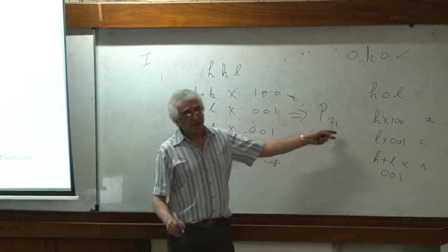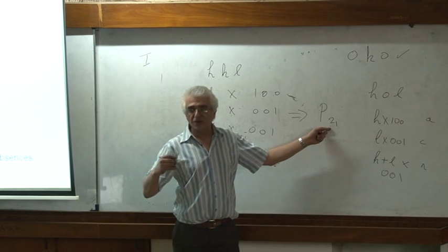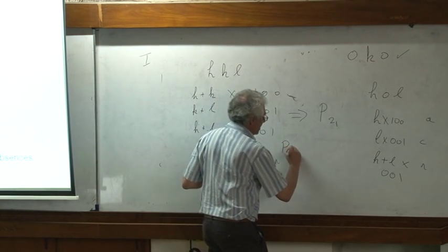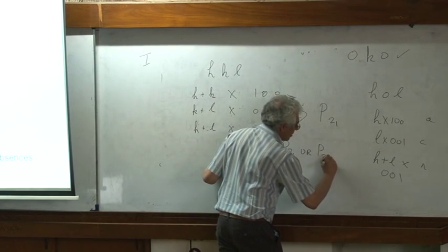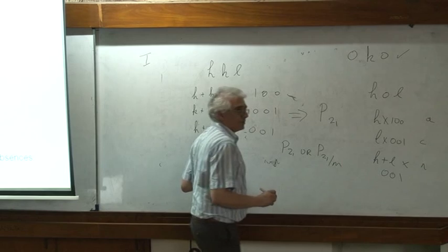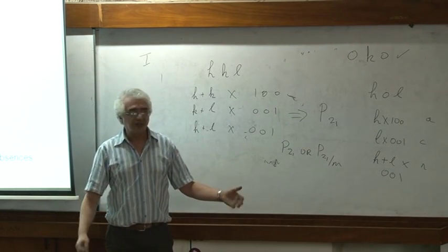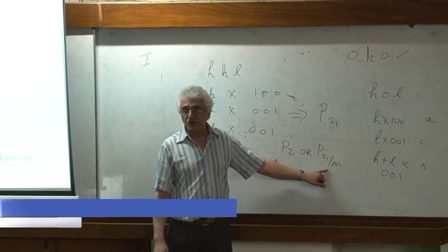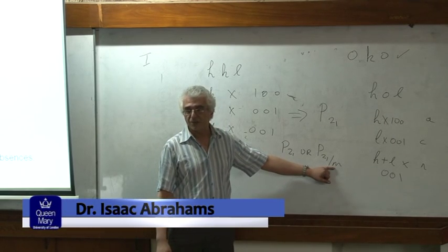So, I don't have any other translational symmetry. This has to be one of 2 possible space groups. So it's either P21 or P21 over M. We can't use systematic absences to tell us about point symmetry. So I can't tell if the structure is centrosymmetric, and I can't tell if there's a mirror plane present.